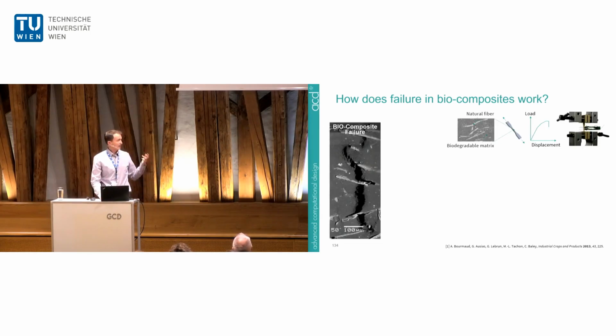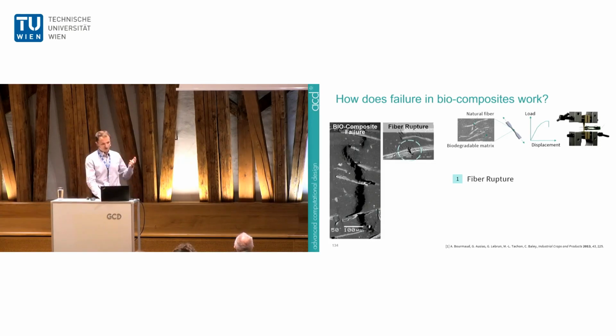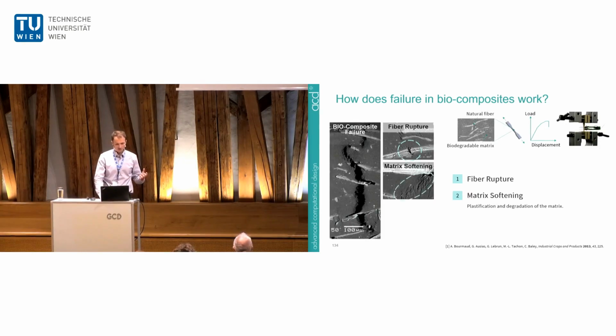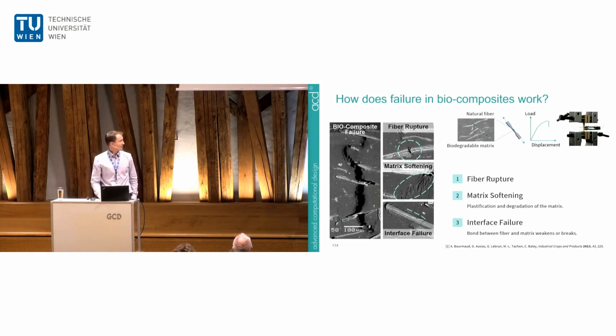And this is how the ultimate failure of the biocomposite can look, if you pull just hard enough in this direction. Just before this failure, you may observe some micro damage in the individual components, but what exactly happens here inside? We can distinguish between three main failure mechanisms. First is fiber rupture, where the fibers themselves fail. Then there's matrix softening, where the glue or the polymer surrounding the fibers degrades. And then there's interfacial failure, where the bond between the fiber and the matrix weakens or breaks.